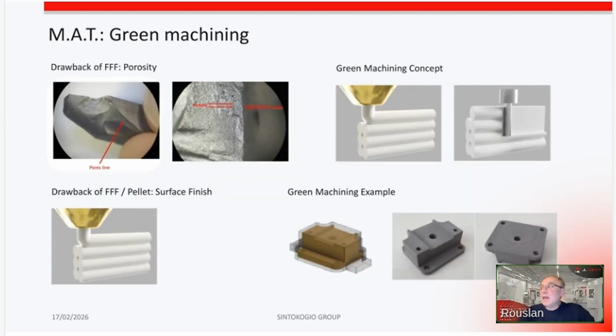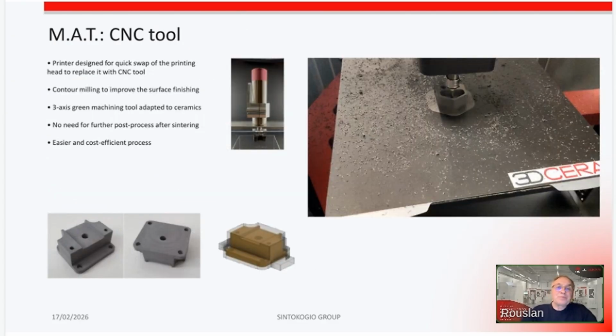And finally, as I said, all these heads are combined with green machining. So you over extrude your part and, without moving the part from the build plate, still fixed after the printing, you just remove the upper layer of the part to enhance the overall density, but also to enhance the roughness of the part.